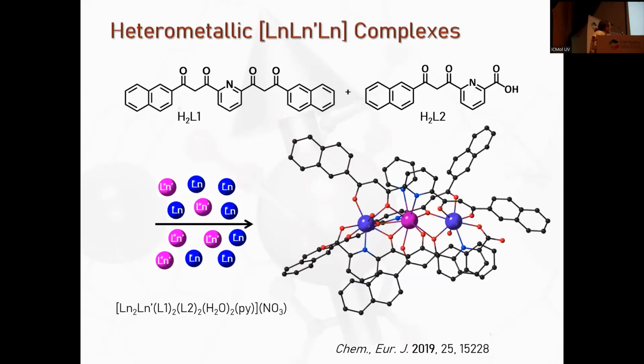From the laboratory, we were able to exploit this methodology, which relies, I didn't mention that, on this question: why are the distances on one side larger than on the other side? What is the reason for this? Well, the reason is that in this coordination system, we see around the metals combinations of these tridentate chelates with these bidentate chelates. So if around this metal you have a majority of these larger chelates with respect to these smaller ones, the bond distances would be larger than in the opposite case, where the bidentate chelates predominate with respect to these other chelates.